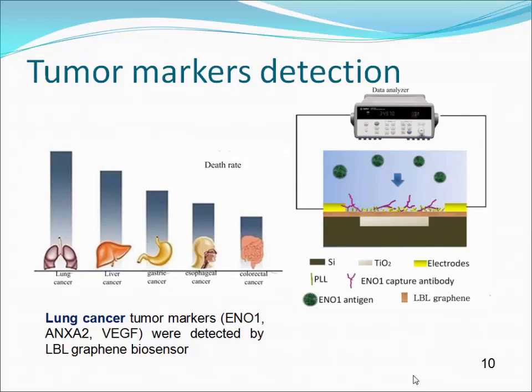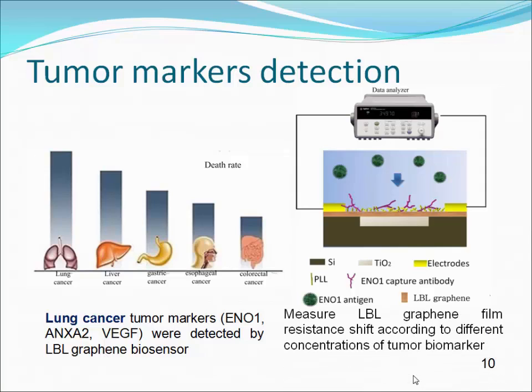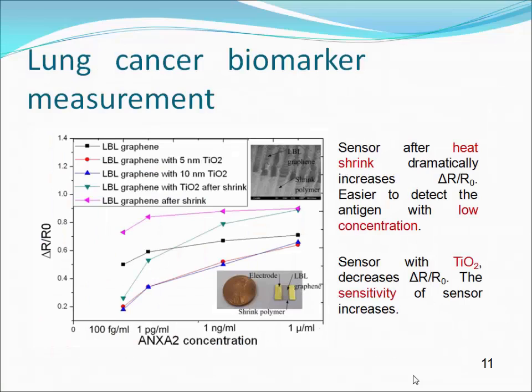Lung cancer has the highest death rate in China so far. According to the paper published, there are 3 important lung cancer tumor markers, ENO1, ANXA2, VEGF. We detect them and measure the layer-by-layer graphene film resistance shift according to the different concentrations of those tumor markers. This is our experimental result. We can see from the picture that when the concentration of ANXA2 antigen increases, the resistance shift of the graphene film